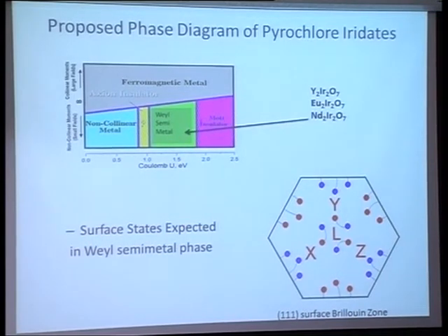So these ab initio calculations give you this kind of phase diagram as you change the Coulomb interaction U. There's another parameter here, the magnetic field, but I won't talk about that. What they tell you is that there's a range of parameters, which we believe is actually physical for several of these materials, where this Weyl semimetal is realized. If you increase U, you get a Mott insulator. The fact that you have some tunability in this first element helps. Even if you find something in the Mott insulator phase, you can find another one that lowers the correlations and may help you get into this Weyl semimetal phase.